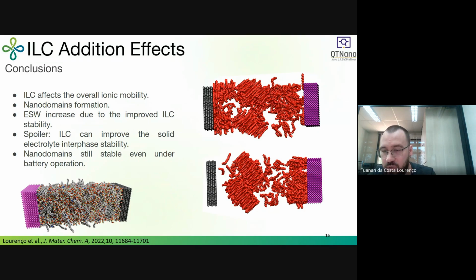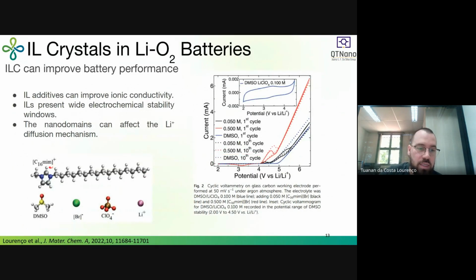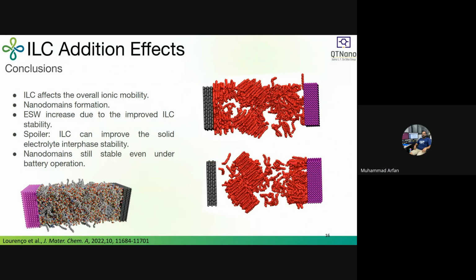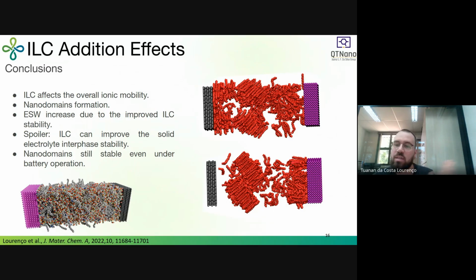Here, it's hard to see this double layer on the surface because of the size of the molecule. So this part here is where the charge is. This part is interacting with the electrode, and this part is not interacting. So somehow we can say that the double layer that we expected will be within these chains. If you look here, can you see that we have the chains pointing to the other side? So we still have these double layers, but the problem with this system is that we have a lot of different molecules, different species, so the double layer is not well defined. If it was just an ionic liquid, you would see positive, negative, bulk, positive, negative, almost a mirror effect.